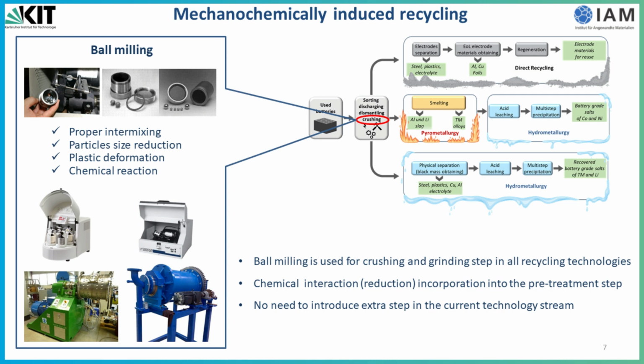As I told before, the crushing step, or so-called ball milling, is introduced in almost all recycling technologies. In our approach, we incorporate a chemical interaction, or so-called reduction reaction, into this pretreatment step. Therefore, there is no need to introduce a new extra step in the current technology stream. It is known that during mechanochemical treatment or ball milling, material goes through proper intermixing, particle size reduction, plastic deformation, and most importantly, chemical reactions. And this is the core of our approach.